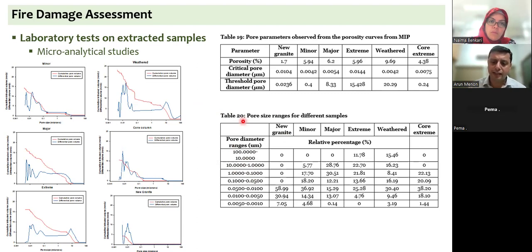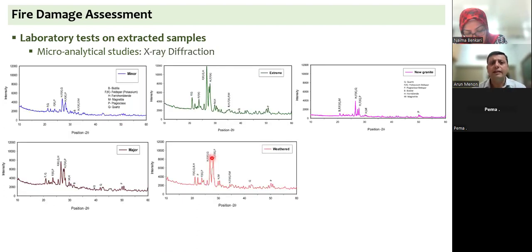So this was some insight we were able to get in different locations of the stone, in different stages of the fire damage of the stone itself. We then did X-ray diffraction studies to understand the type of crystals and minerals that are forming in the stones affected by fire. But here, really what was happening is the crystal forms were slightly changing, and that was due to expansion due to fire, and that was being captured, and that could also explain why the porosity was getting affected in some parts of the stone.